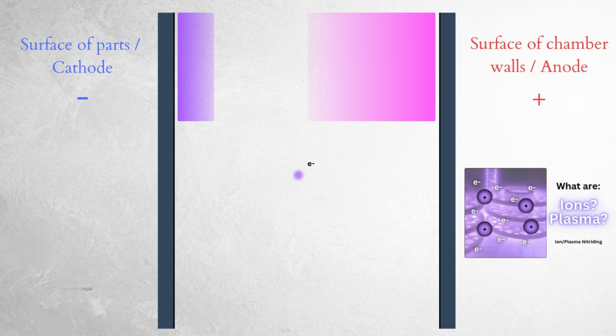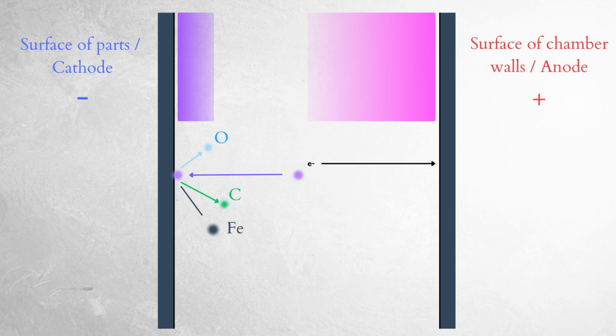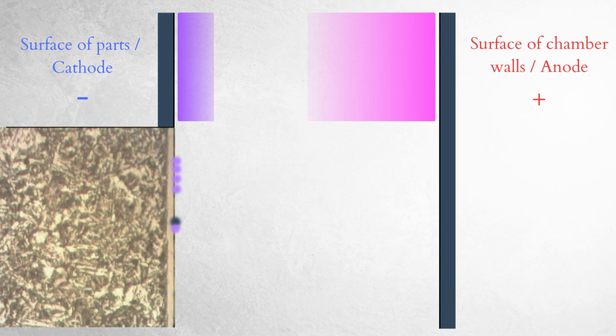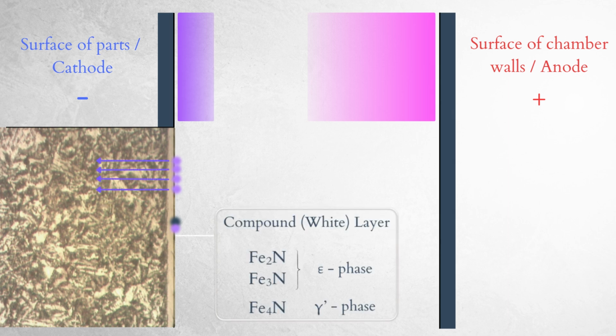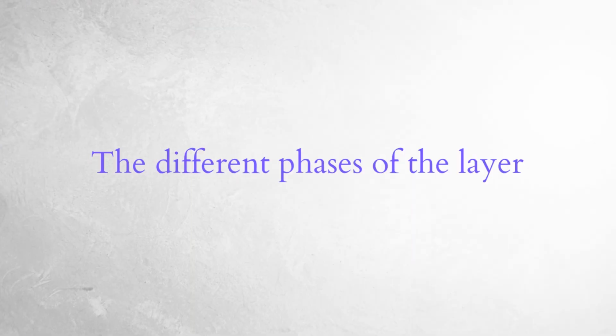In our video on the ion nitriding mechanics, we explained that ions, radicals, and excited neutral species interact with the surface. This helps heat the part, clean and activate the surface, and supply active nitrogen. Nitrogen then diffuses into the steel. When the nitrogen concentration in the first few microns near the surface becomes high enough, it exceeds the solubility of nitrogen in ferrite at the process temperature. At that point, iron nitrides form at the surface. This is why the layer is called the compound layer.